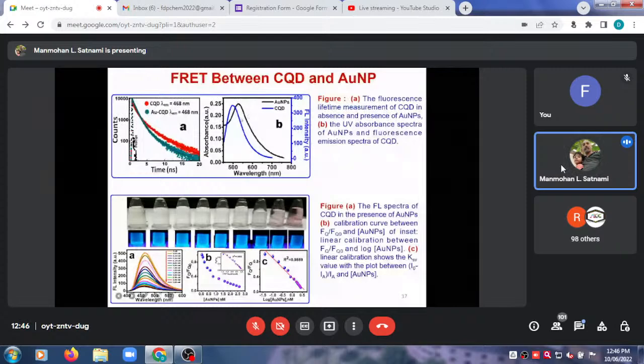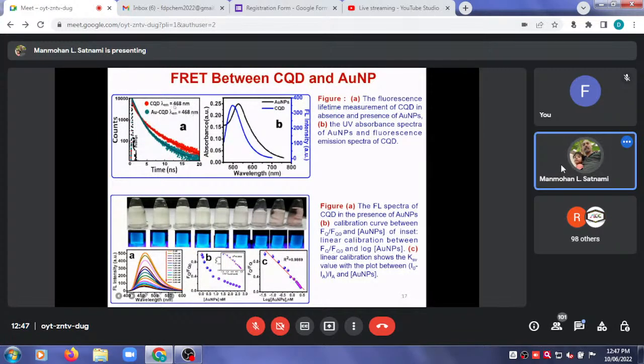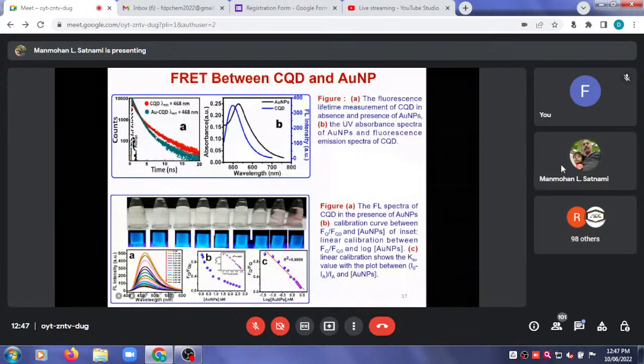And another point that is very important is that if any quencher or any fluorescence acceptor is present with a fluorescent donor, say for example carbon quantum dot, then the fluorescence lifetime of carbon quantum dot should be decreased. You can see the red line is the fluorescence decay curve for carbon quantum dot, which is excited at 468 nanometer, emission at 468 nanometer. And when gold nanoparticle is added to the carbon quantum dot, then the blue green line appears, the curve for the donor and acceptor pair.